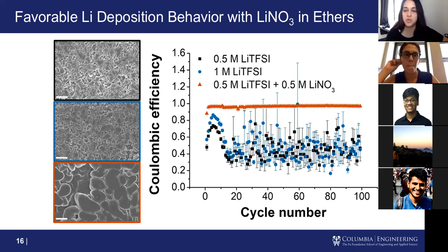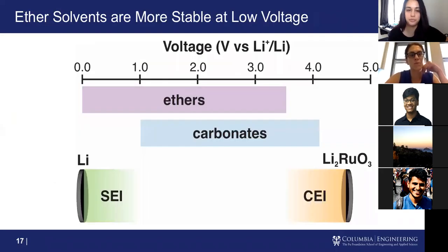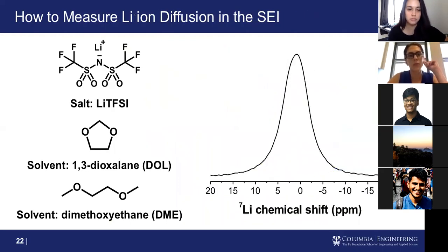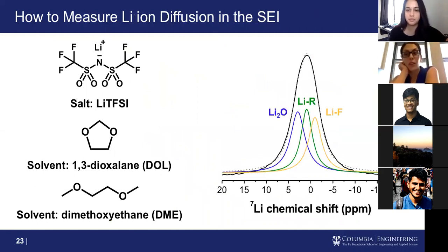Okay, and then for slide 23, it says, why doesn't the spectral resolution discern the different peaks? So it's because of an NMR property of lithium-7. Lithium-7 is very naturally abundant, about 93%, which means that in any lithium compound you're going to have lots of other lithium atoms around. That means those lithium nuclei can couple with nearby lithium nuclei, and that causes broadening and smearing out in the spectrum. What you could do is measure lithium-6, where you have more spin dilution and get better resolution, but it's a lower sensitivity nucleus, so there are trade-offs there.